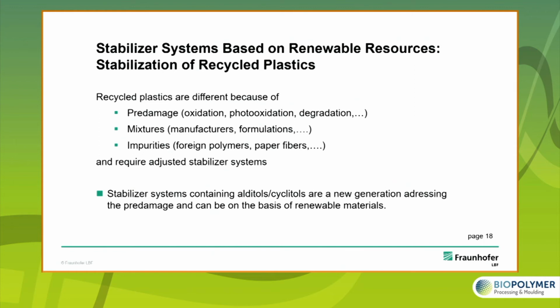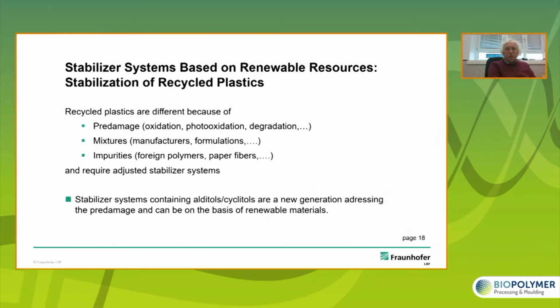First of all, we have to understand that recycled plastics are different to new plastics because very often they have a pre-damage by oxidation, photooxidation, degradation of molecular weight or other structures, differences in structure. Furthermore, recyclates can be found of different formulations, different technologies, processes, and thus they are non-identical to a pure new material. Very often, with high-value methods, recyclates show impurities, for instance, by foreign polymers or other materials, could be paper fibers, glue, residues, and so on and so forth. That is why recyclates require an adjusted stabilizer system.